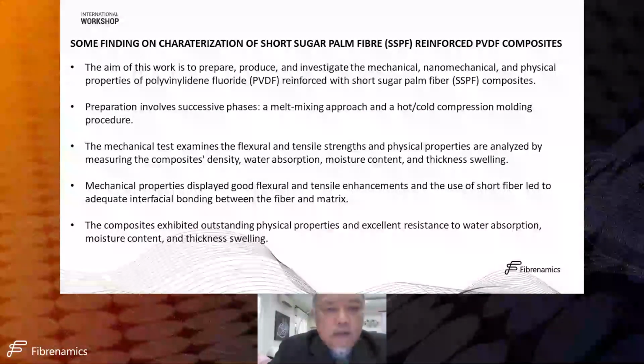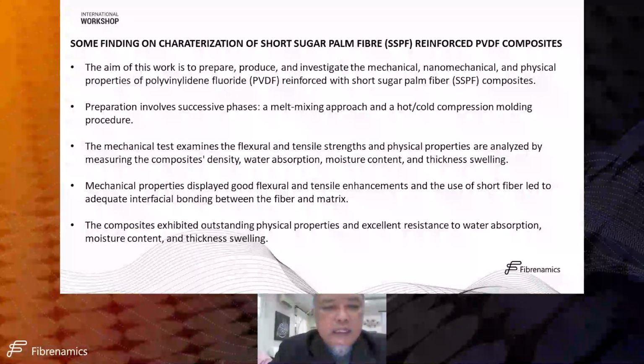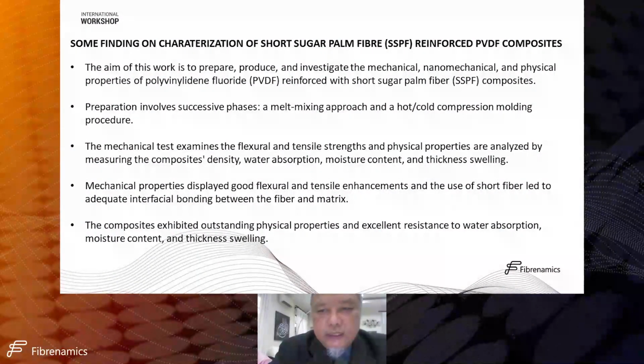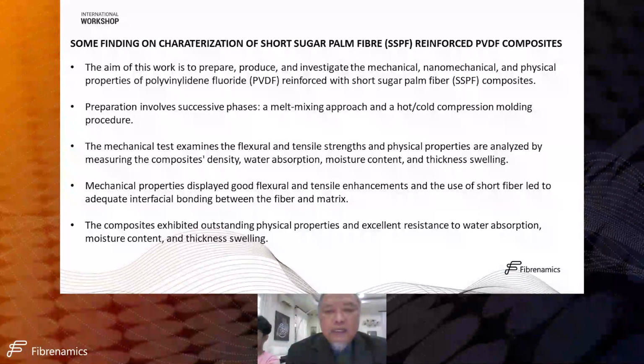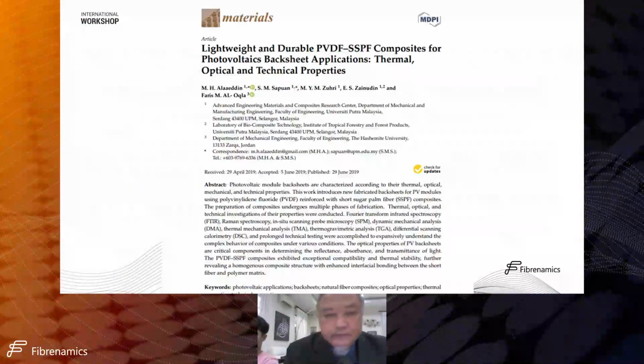And we carried out the study of the mechanical testing and also physical testing: density, water absorption, moisture content, and thickness swelling. And the mechanical property of this material displays good flexural and tensile enhancement. And the use of sugar palm fiber led to adequate interfacial bonding between fiber and matrix. The composite exhibited outstanding physical properties and excellent resistance to water absorption, moisture content, and thickness swelling.